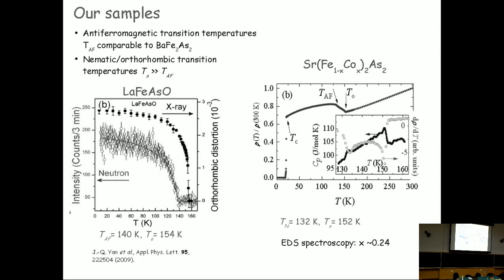So these are our samples. We studied this LaFeAsO. This is the undoped, original grandparent iron pnictide that was discovered first. Then it was abandoned by most of the scientific community because it was difficult to grow, much more difficult than the 1-2-2 system. But still, we have good samples of these, and we have this sample that shows a magnetic Bragg reflection by neutron scattering, showing that the magnetic ordering temperature is about 140 Kelvin. And then you have the structural separation of the Bragg peaks that goes to 0 at a temperature that does not coincide with the magnetic ordering temperature. It's more than 15 Kelvin of difference. So this is 140 Kelvin, 145, 154 Kelvin. They are pretty much split.